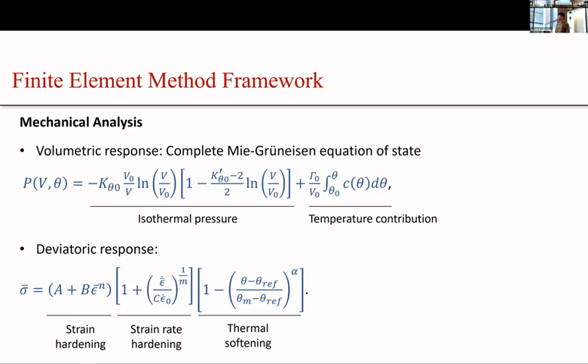Okay, based on my understanding, the shock stress in our case is still considered low because we still see that two-wave structure. It's not even an overdriven shock, so I wouldn't anticipate any phase transition at this stress level.